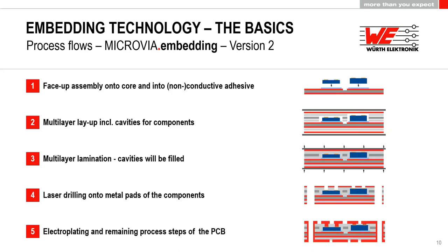microvia plating here. If we have different component heights, we would rather need to go to version 1 because there the difference in height doesn't affect the microvia because we drill through the epoxy glue and onto the pad where we have always the same depth of the component. And in version 1, only the thickness of the component decides how thick the actual build-up will be.